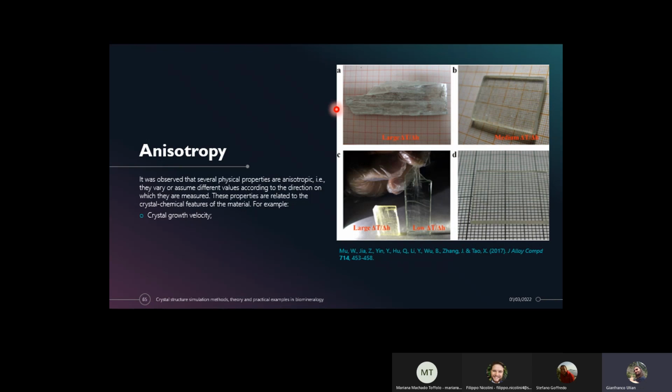If some molecules adsorb on a crystal face, on the nucleus of the crystal, it may hinder the development of that face. So you can control the elongation and the shape of the crystal according to need, and this is what nature does in a living system.